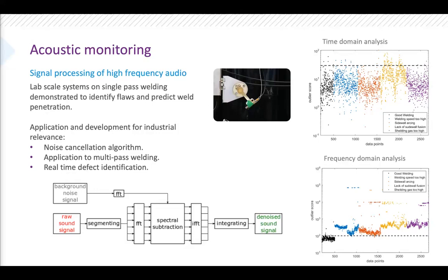Then we were moving into analysis methods of the signal, and this was quite early work, but we did display quite a good correlation between our baseline welding conditions and then a suite of different parameters that can lead to common flaws like lack of sidewall fusion. So in the test suite, I don't know if you can make out the graph, but we were looking at sidewall arcing, travel speeds too high, interruptions to gas, those kinds of potential situations that might lead to a flaw, and we can hear them and classify them within this sensor. So next slide, please.